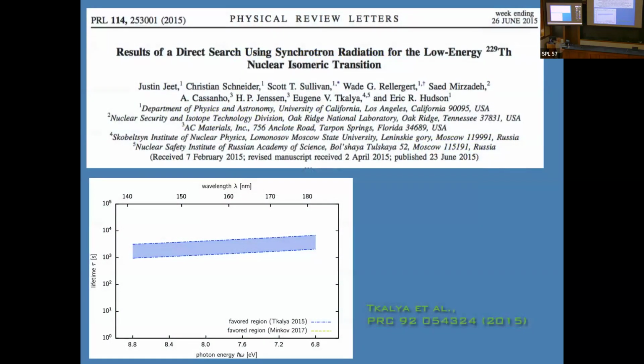There are some interesting things looking back, but we had no conclusive evidence of the transition, and so we made what we called our exclusion plot. This was what we did for many, many years. On here is the possible wavelength of the transition. Here is the possible lifetime. This blue region is where we thought it would be. We did some work with Eugene to figure this out from the nuclear physics. And what we were able to exclude is shown in red here. That's about 90% confidence.